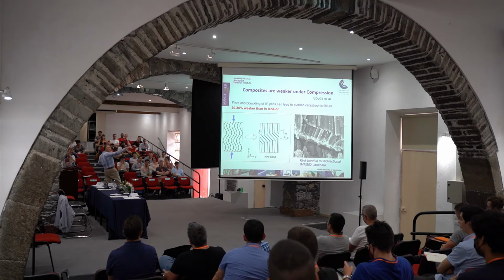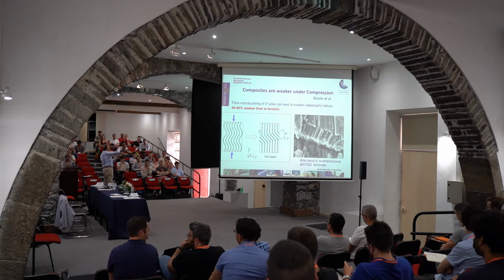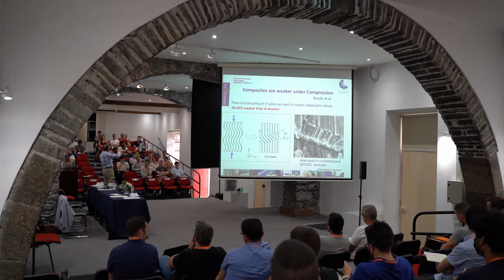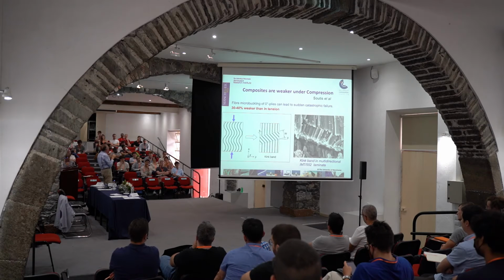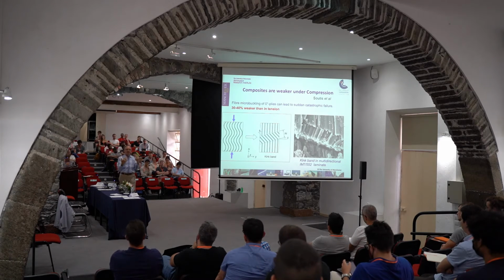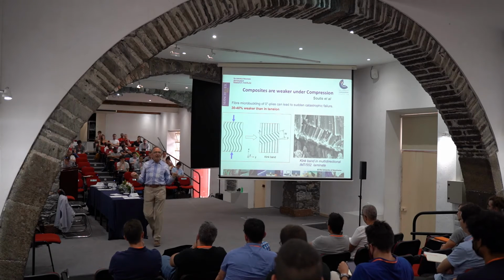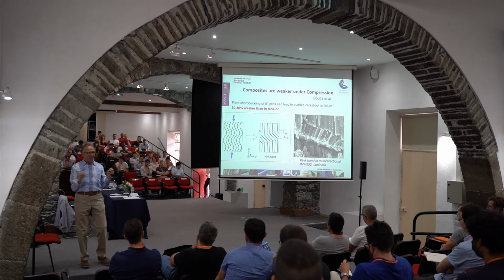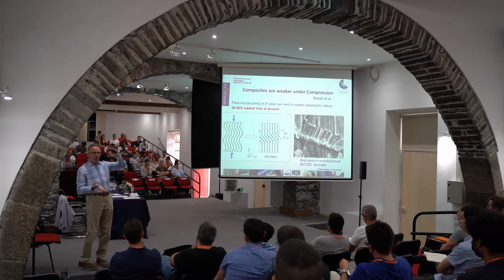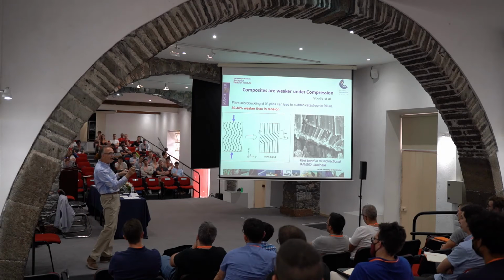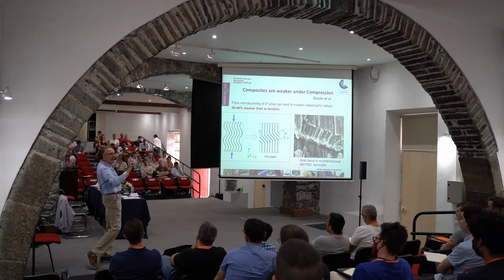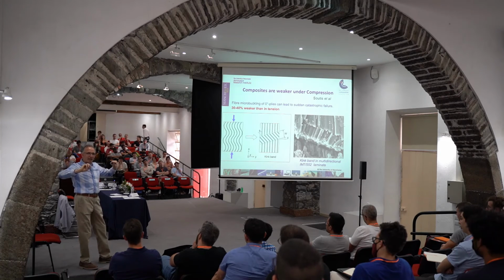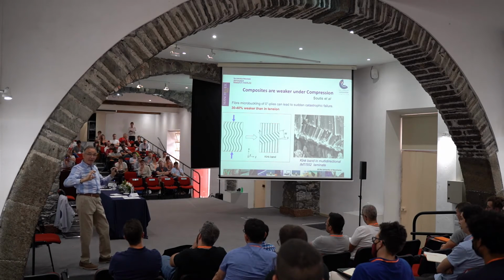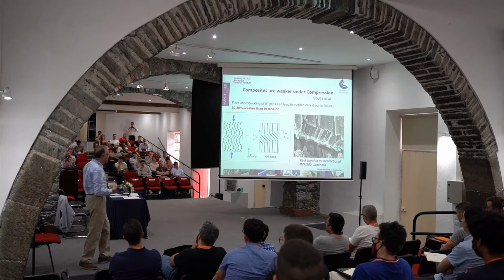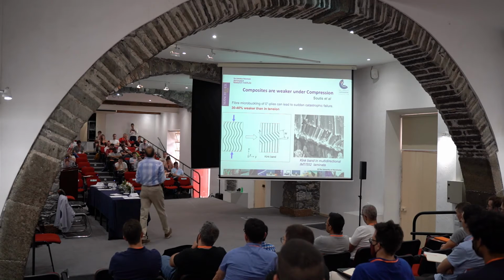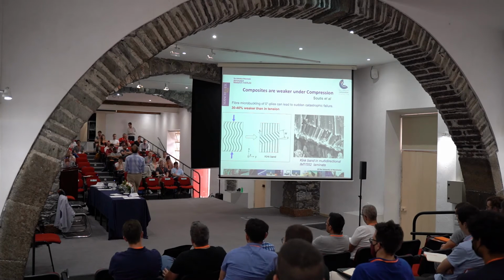And this is the kink band, where at the point where you have the large deflections, the fiber breaks and creates this kink band, which, in the microscope at a lower magnification, resembles a fatigue crack in metals. And it propagates with the applied load. And when it reaches critical length, it goes boom. And the decibels that this kind of fracture creates, it releases all that energy, that we try to calculate, and we need that as well, is equivalent to the decibels created by the takeoff of Concorde.